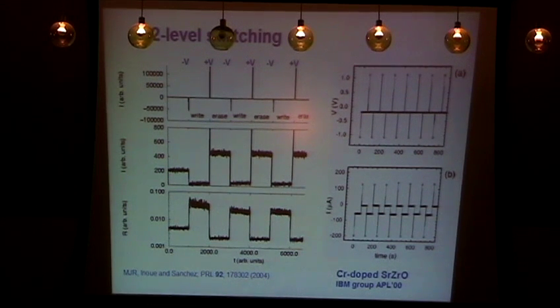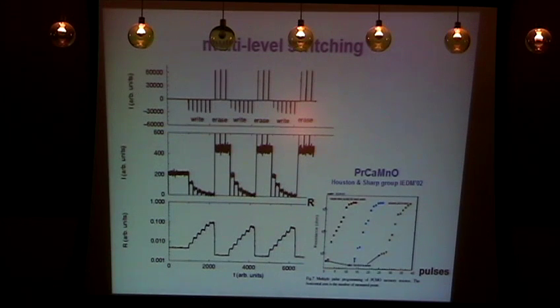So these results do not look that impressive, but the less trivial thing that gave us some confidence that this model was capturing something non-trivial is that when you put many pulses that can be erase or write, you see that the behavior is quite different. If you apply the erase pulses, the system is saturated at the maximum current and does not go beyond. Therefore, when you invert that, you have the resistance being at the lowest level. And then when you apply a set of write pulses, you get a systematic suppression of the current.